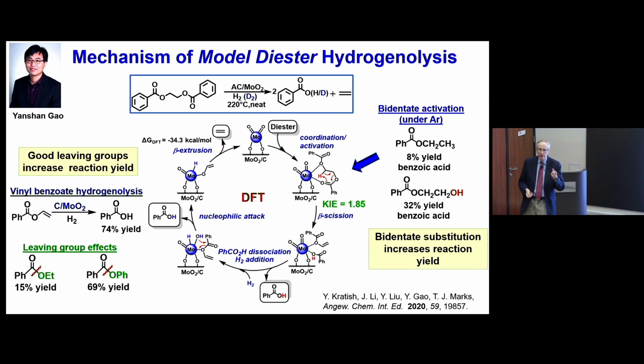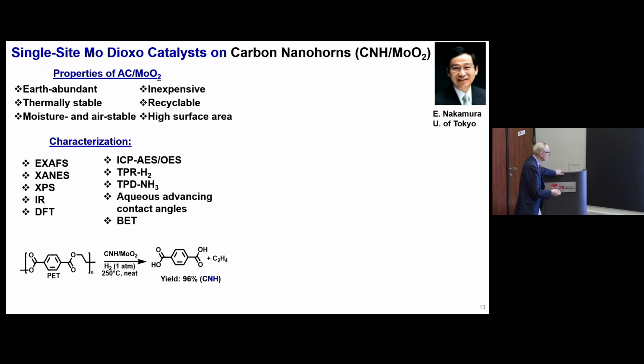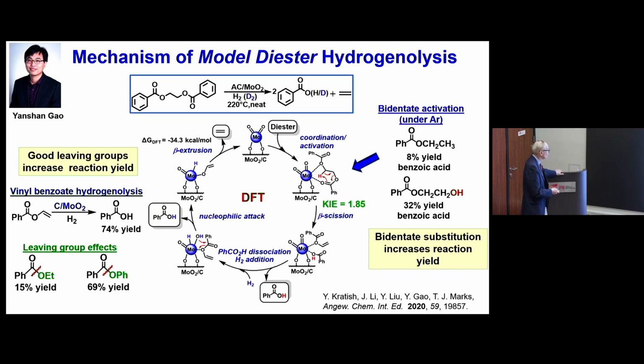One is the activation energy. Are the experimental and calculated ones similar? That's easy to do. The other is kinetic isotope effects. Do the calculated and real agree? And then there's a process that kicks off a benzoic acid, and then you follow it through, and there's a nucleophilic attack, and you kick out another Bronsted acid and ethylene, sorry. And we can do some model reactions that verify the mechanism. So we understand that pretty well.